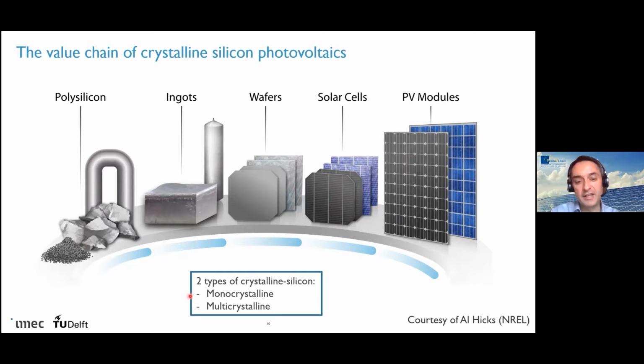In principle, we can distinguish 2 types of crystalline silicon, depending on the type of wafer. If we have a monocrystalline silicon wafer where the wafer is one single crystal, then typically we can get the highest solar cell efficiencies. But we can also make multicrystalline silicon wafers. These are wafers which are a little bit cheaper to make, but you have multiple crystalline orientations in the wafer, and the efficiencies you can reach at cell level are a little bit lower.